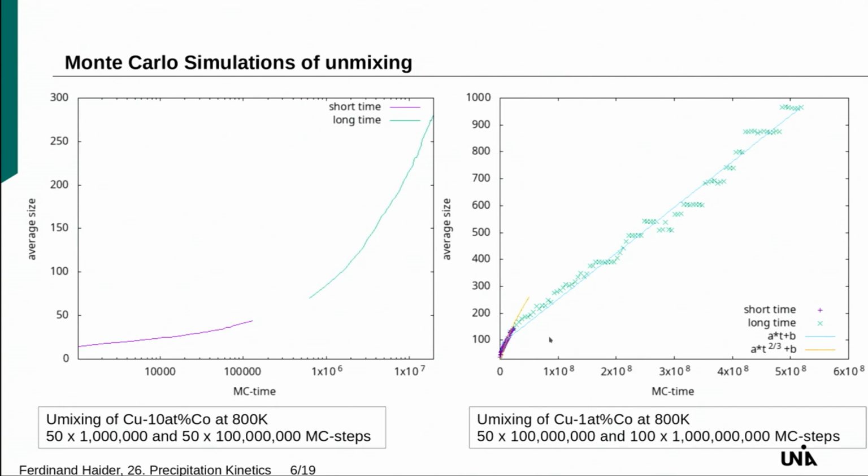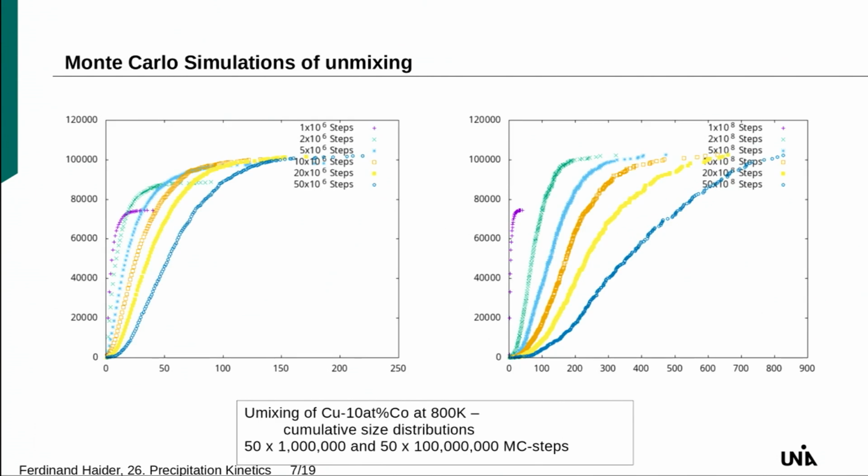So that's the size plotted as a function of time, and you see that this t^(1/3) law, or the average number of atoms in the cluster being proportional to time, is well met. This line here would be this t to 2/3, which still is okay, I would say. So far, it's okay. The very simple laws might be considered to be confirmed.